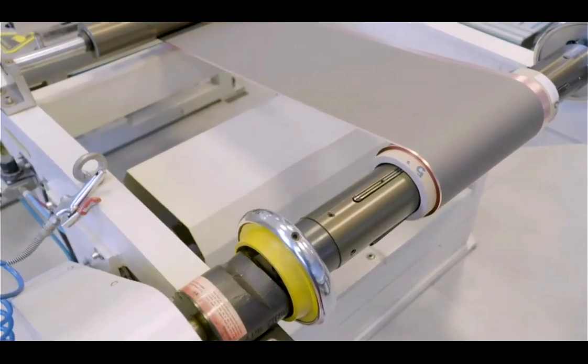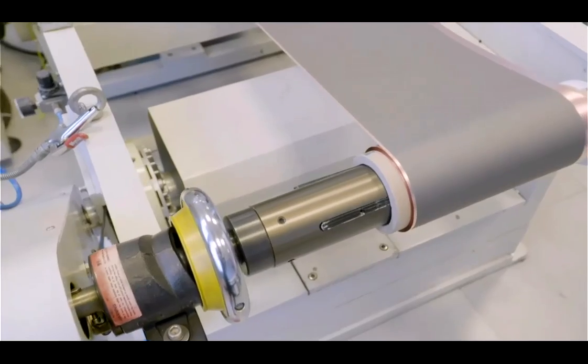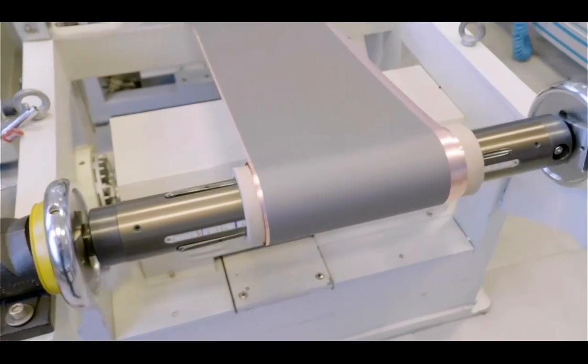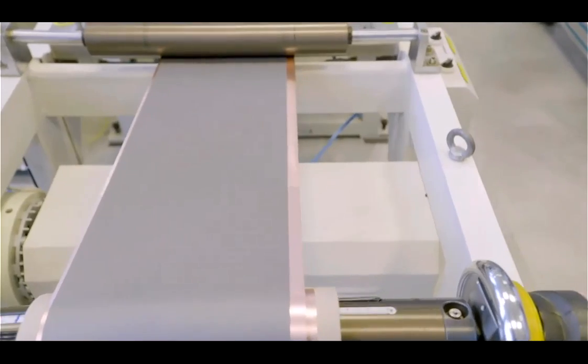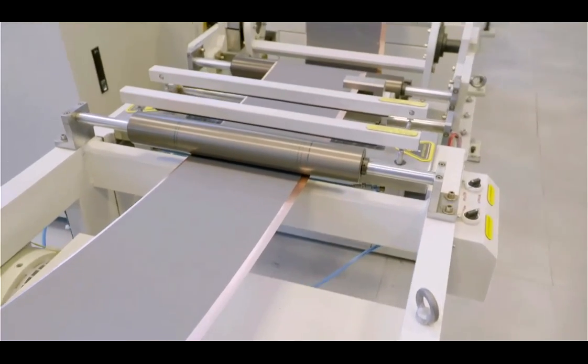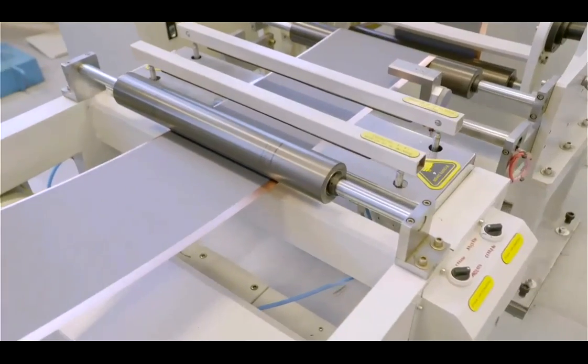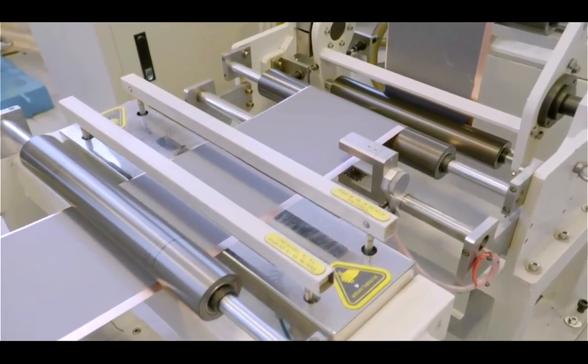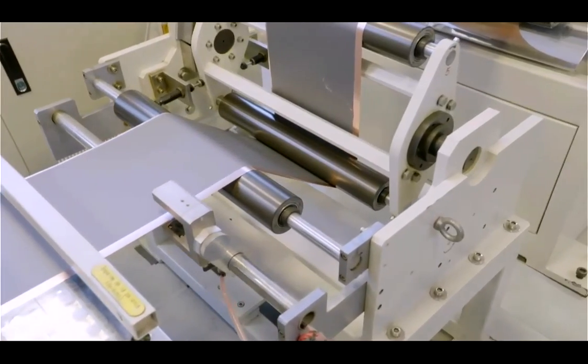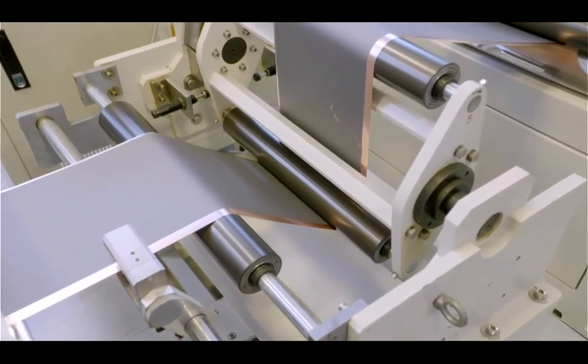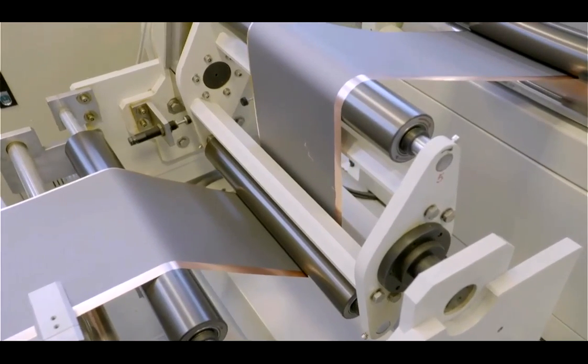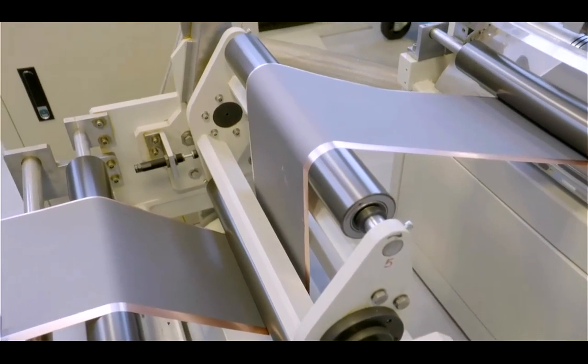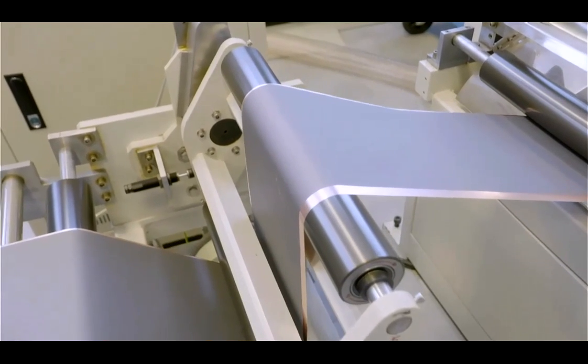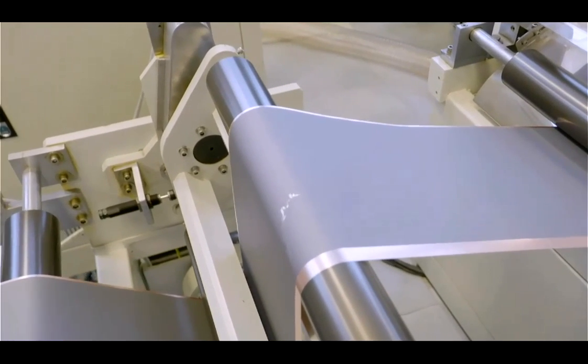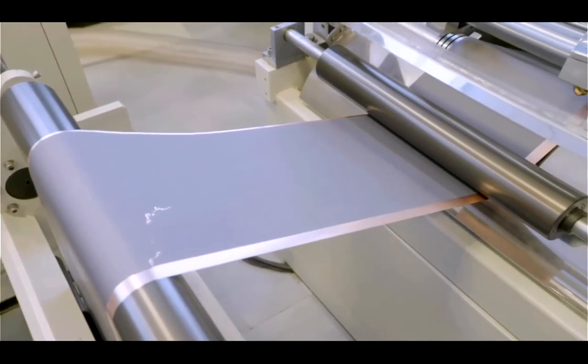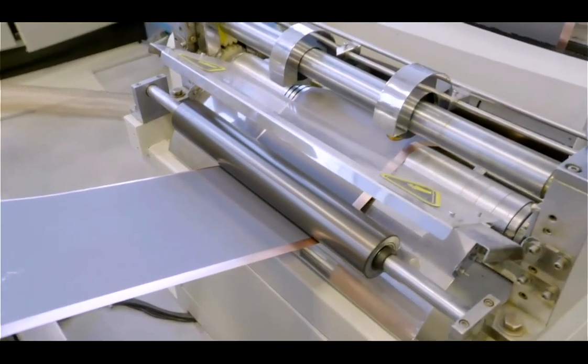So that means that we have to reduce the thickness of the electrodes. From the other side, with the calendering, we will homogenize the surface of the electrode, and this will prevent some possible short circuit during the working of the cells. Now in the images, you are seeing a lot of rolls and devices, but all of them are just guiding systems. We have to make sure that the electrode goes in the right direction in the calender.